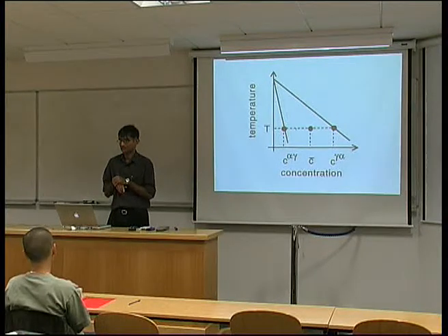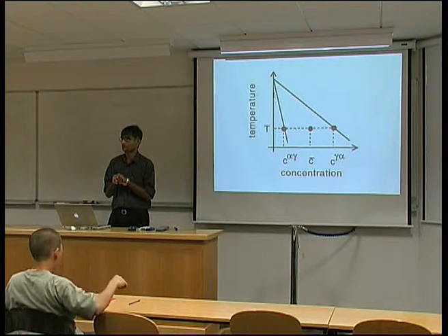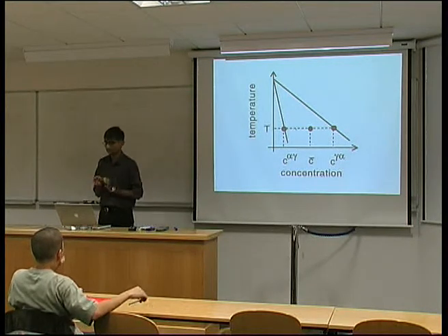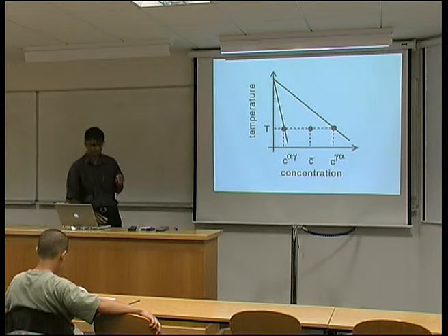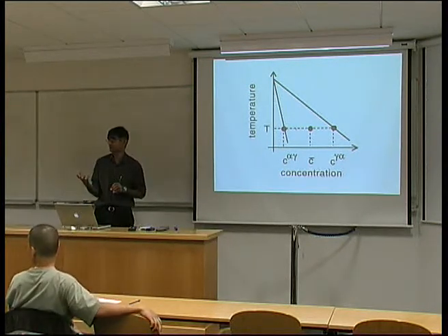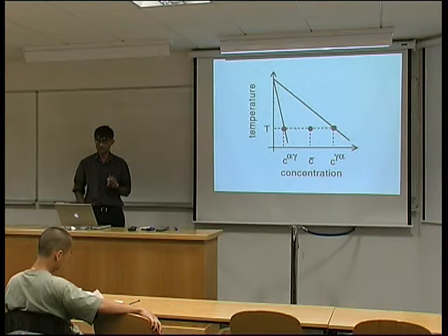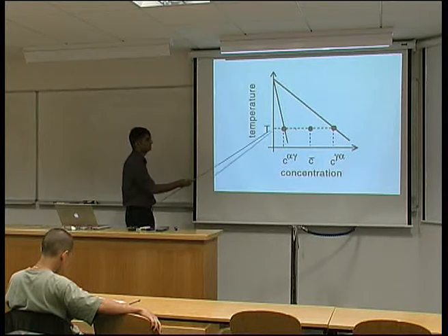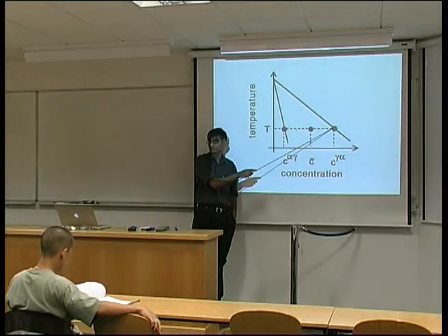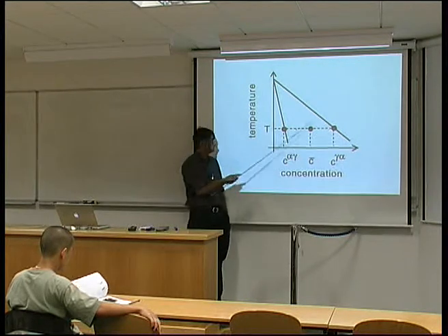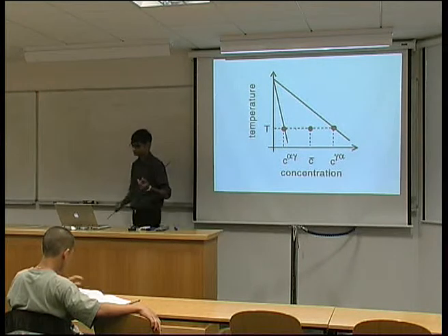Now, in the last lecture, we dealt with diffusion control growth in binary systems, and the particular binary system that we considered was the iron-carbon system, although it could have been anything in which one species dissolves less in the product phase than in the parent phase. And if you remember, the compositions at the interface were given by a tie line of the equilibrium phase diagram for the transformation temperature at which we were doing the calculation.